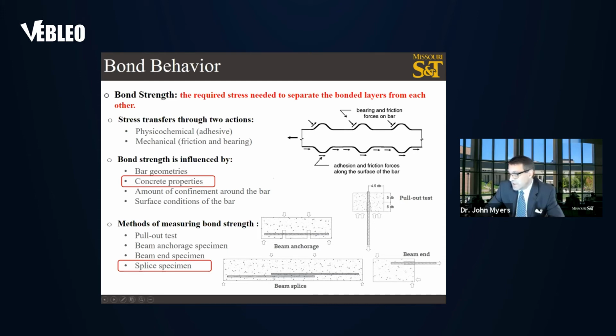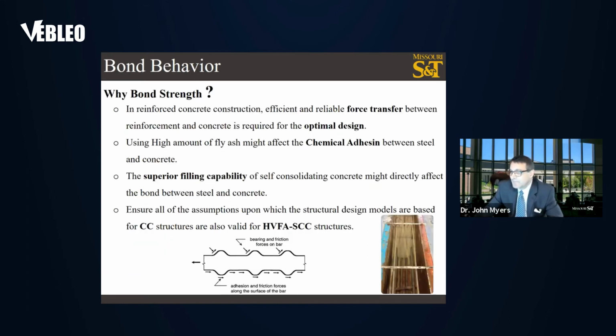In our particular study, we focused on the beam splice test because this test actually puts the bars in flexure and is more representative of an actual reinforced concrete beam bond behavior. Why bond strength? As mentioned, it's very important in terms of the force transfer, and using a high amount of fly ash could affect the chemical adhesion as well as the frictional resistance between the bar and the concrete. So we're very interested to see how well this performs.